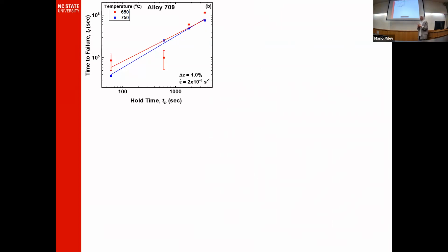When we introduce additional time to the cycle, which is the hold time, the cycle time in general increases by a factor greater than the factor corresponding to the reduction in the number of cycles, or the creep fatigue life of the material. That's why we observe an increase in time to failure with hold time, while a decrease in the number of cycles to failure with hold time.